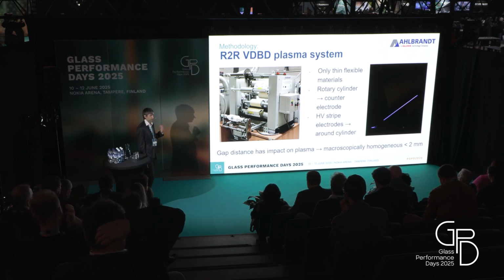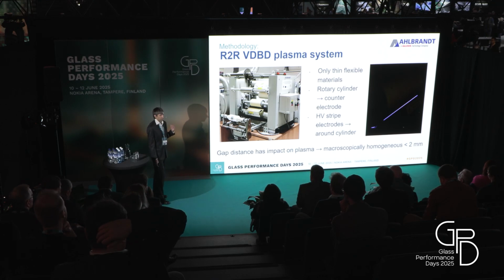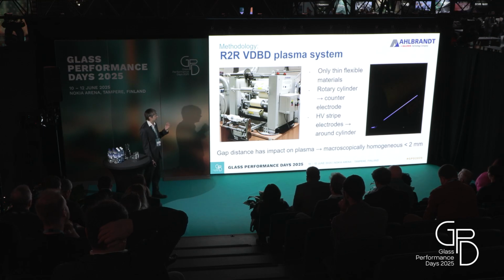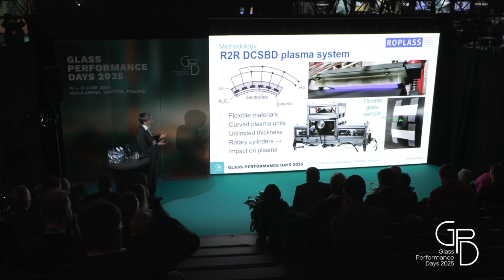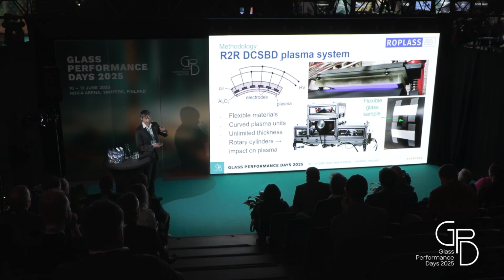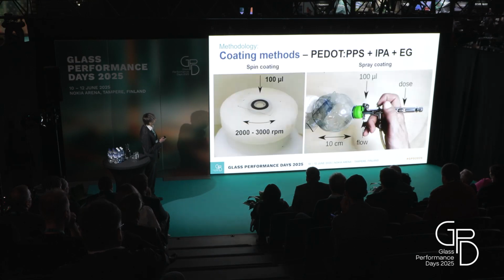But for example, for some thicker foils, like those used for laminated glass, there is not enough space in 2 millimeters to pass the sample. So this has a limit. Our previously shown plasma system has no limitation for the thickness of the coating, because you just expose only the surface to the plasma active area.